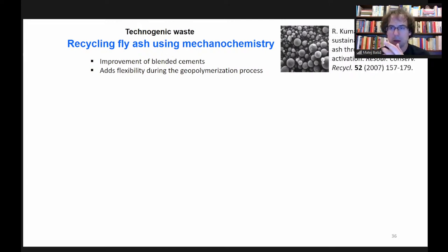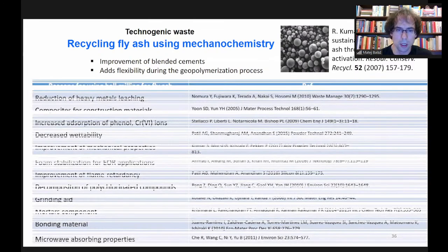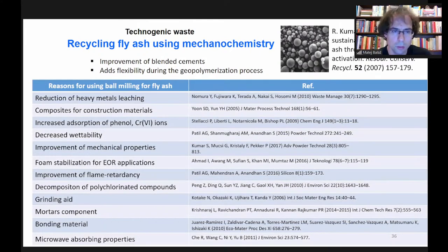And as I mentioned at the beginning, there are a number of works by an Indian group which dealt with the mechanical activation of this waste material, which can lead into the process called geopolymerization. But also, usually this produced material is very good for cement production and in the concrete industry. Here is an overview table about a number of applications for which fly ash, when it is mechanically activated, can be used. So we have composites for construction materials, or it can even be used as a grinding aid, or can be part of mortars.